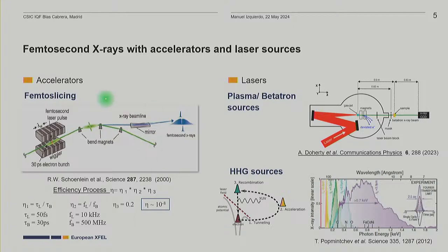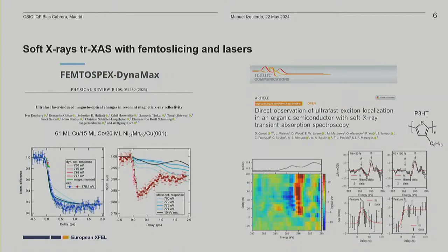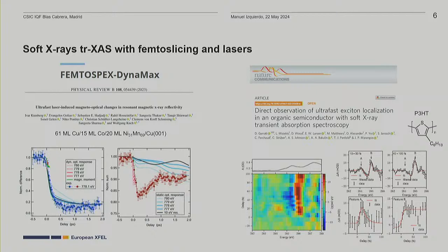The advantage of femtoslicing is that you can produce both soft and hard X-rays, and both have been used up to date. You see here one of the latest experiments published at the FemtoSpeX station at BESSY, where they used femtoslicing to study ultrafast induced magneto-optical changes using resonant reflectivity in this kind of compound. High harmonic generation sources have been used also to study, for instance, this compound that has application for light harvesting. You can get some dynamics, but you need a very detailed model in order to understand what is going on in this data.